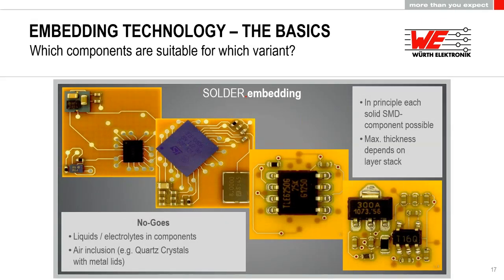Which components are you able to use? And here I have a small chart for the soldering of the components onto the inner layer as well. In principle, each solid SMD component is possible to use as long as the maximum thickness of the component is not thicker than the layer stack. It's not possible, for example, to use a 3.2 millimeter capacitor and embed it into a 1.6 millimeter buildup. No component is allowed to stick outside of the PCB, so it needs to fit into the stack up.